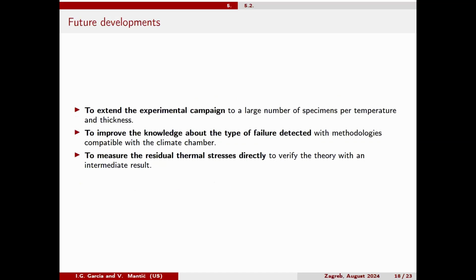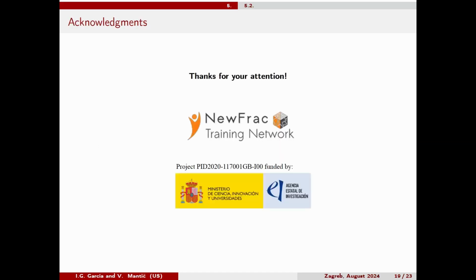So to finish, we are planning to do, of course, a new experimental campaign with more specimens and more laminate thicknesses. We need to improve the knowledge about the failure or the event that we are detecting with the acoustic emission. Actually, we are collaborating with some colleagues already on this topic. And finally, we need to measure the residual thermal stresses directly, because now we are actually measuring the consequence of these residual thermal stresses, that are the critical strength at which the crack appears. But we could actually measure the residual thermal stresses directly in our laminate before testing them, in order to have an intermediate result to compare with our theory. And that's all. Thank you for your attention.